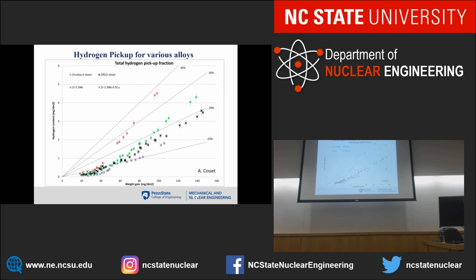So here's showing, just quickly, again from the thesis of Adrien, the hydrogen content against weight gain. Now let's assume that the hydrogen pickup fraction was constant. You would then follow one of these lines: 10%, 20%, 30%, 40%. Clearly it's not constant. It changes and actually increases, going from below 10% at the beginning to between 10 and 20 and higher. And it also is consistently different for the alloys.